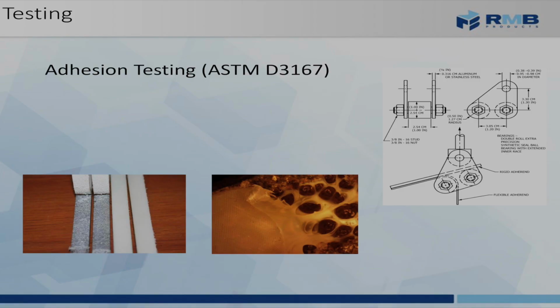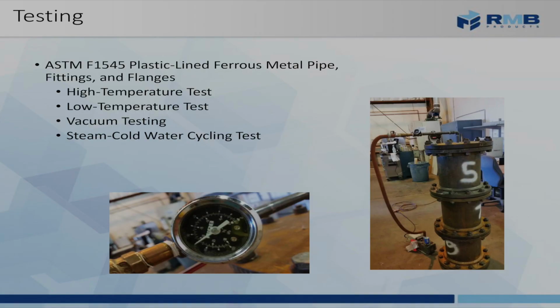The adhesion testing, which is this ASTM D3167, is a method to determine what the strength of the bond is. So this is how we're able to stand behind our vacuum rating, by knowing what the strength of the thermoplastic is to the given metal substrate. And there is a standard for lined pipe. It's ASTM F1545. Section 6 of this standard provides these different tests: high temperature, low temperature, vacuum, and steam cold. These are long-term tests, very expensive, but they're something that we subscribe to when we're trying to qualify a new product, a new combination of resin with metal.